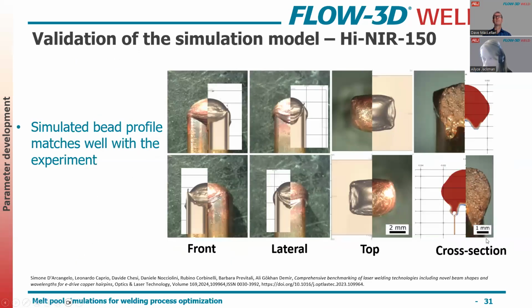Let's look at the next screen. We get a very good agreement, not only in terms of the bead profile, but in terms of the actual shape of these beads, these kind of folds right here. So this is very surface tension driven kind of behavior, viscous forces. I mean, it's quite phenomenal what we are seeing in terms of the comparison. If it's not obvious, the simulation is on the left in these bottom cases. This is a ray tracing, and then the experiment is on the right.